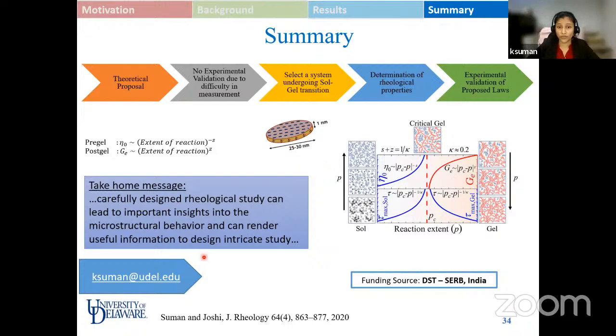Yeah, thank you for pointing that out. So why do I present the results for a volume fraction of 0.2? There is no specific reason for choosing that. It's just concisely presenting the results. I repeated the experiments for different volume fractions till I went up to 0.4 volume fraction, and I get the systematic decrease or drop in the modulus value. So it happens at different volume fractions as well. So it is not specific to a specific volume fraction. It's just the way of presenting. I restricted myself to present only one system so that I can cover more parts.